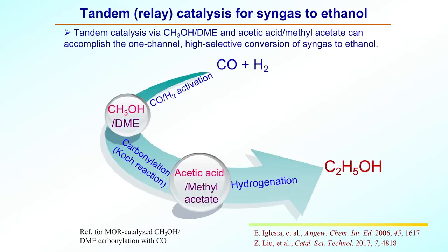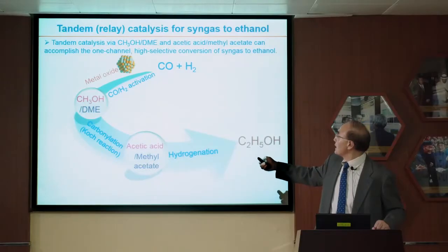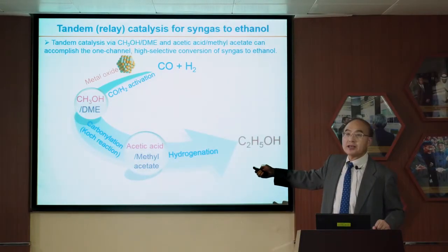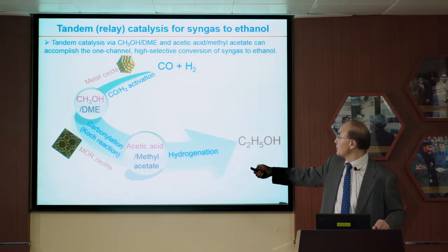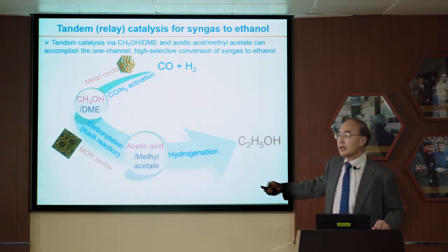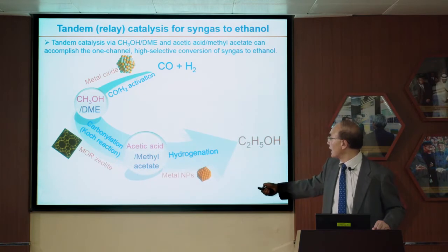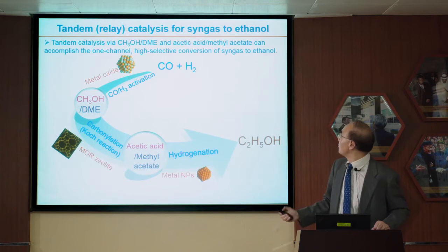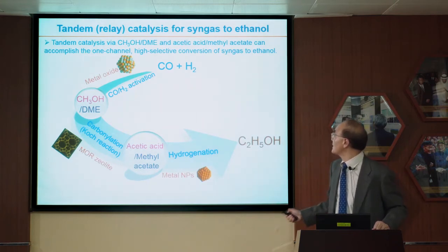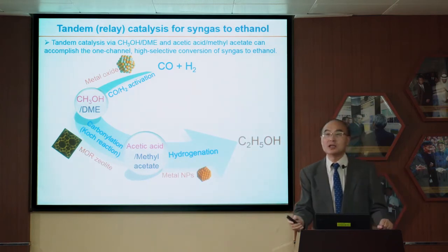So our idea is tandem catalysis via methanol or DME and acetic acid or methyl acetate, by integrating metal oxide for methanol and DME synthesis, MOR zeolite for methanol and DME carbonylation, and metal nanoparticles for the hydrogenation of acetic acid or methyl acetate, which may accomplish the one-channel high selective conversion of syngas to ethanol.